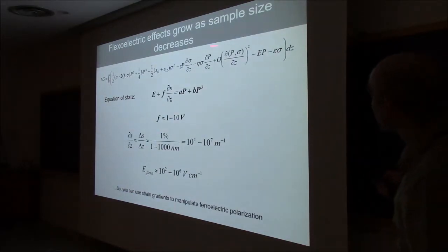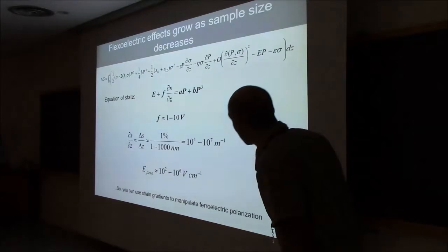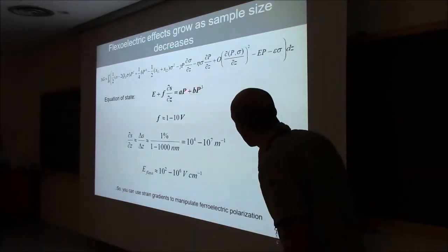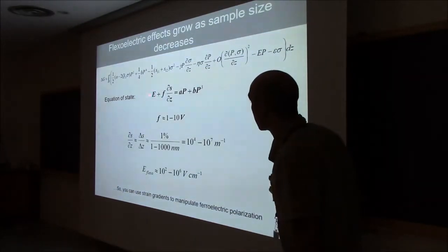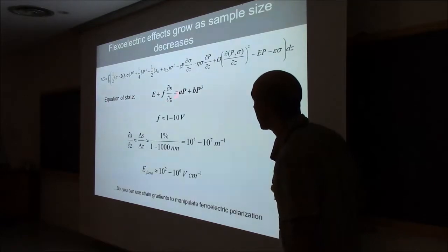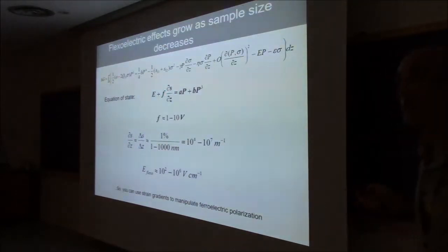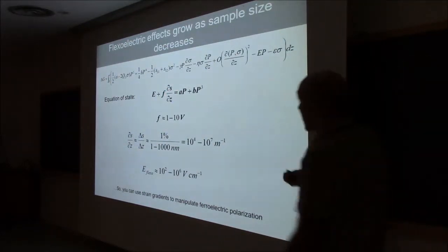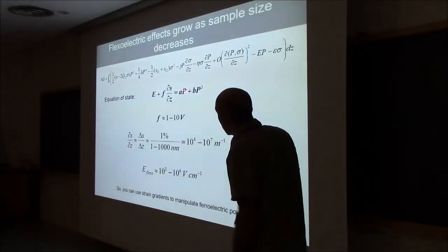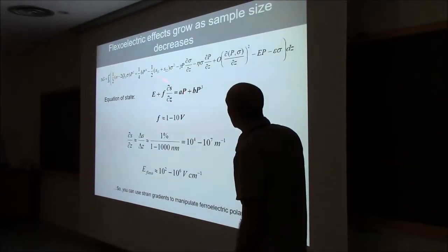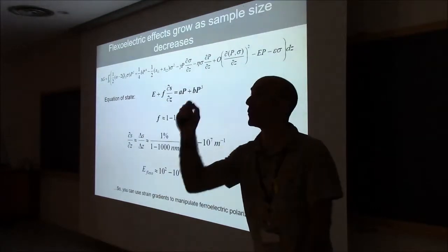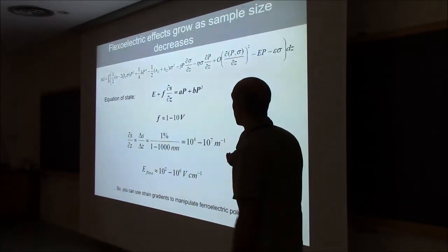You can minimize this, and you can get the equation of state of your ferroelectric in the presence of either an electric field or a strain gradient. And what you can see immediately is that anything that I can do to the polarization using an electric field, I can also do to the polarization using a strain gradient.